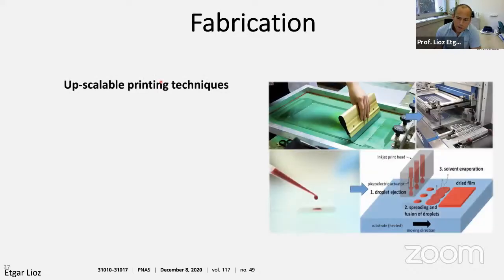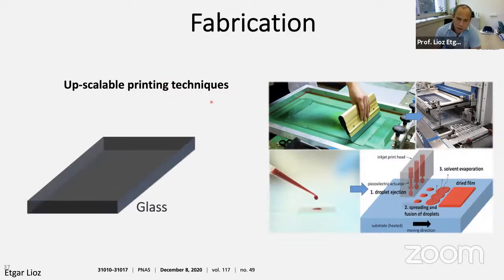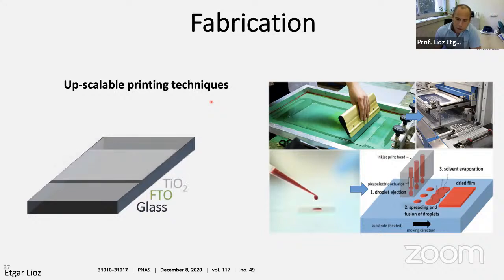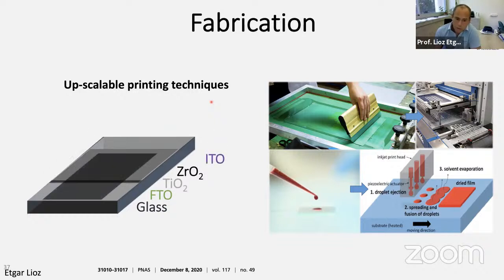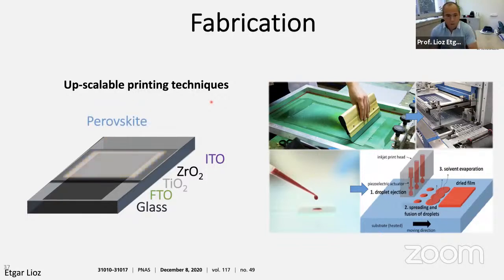What is the fabrication? Fabrication here is also based on a screen printing technique, as you can see here. So usually we start with an FTO glass, and then we start to print the layers. It's a mesoporous TiO2, mesoporous zirconium oxide, and then we print the mesoporous ITO, which we developed in the lab, and we drop the perovskite. So this cell can be done in a few hours, ready, very easily and very, very stable.